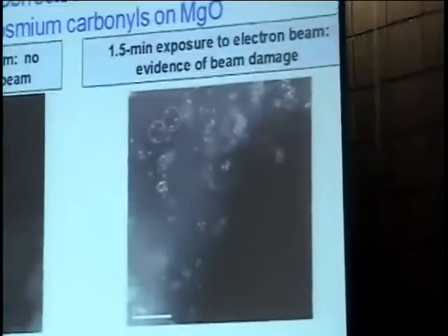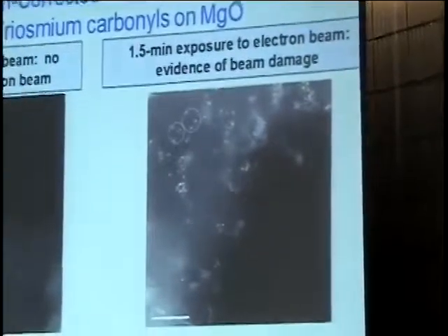The XAFS and the microscopy values match, which says that we've done the preparation effectively, that we've gotten a high yield of the desired triosmium on the support, which is reassuring. It means if we're trying to make simple samples, we succeed. So now let's go to the same sample, but characterize it with better quality microscopy. So this is aberration-corrected STEM.